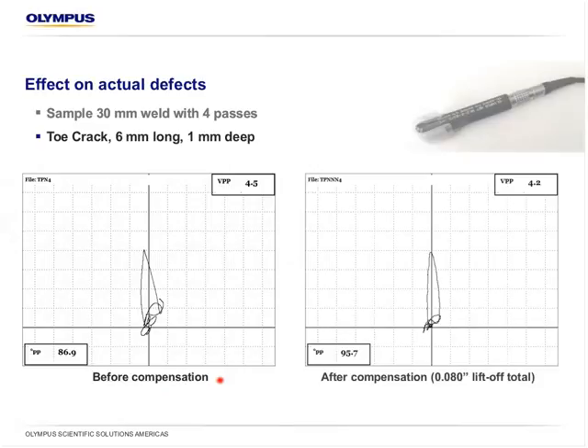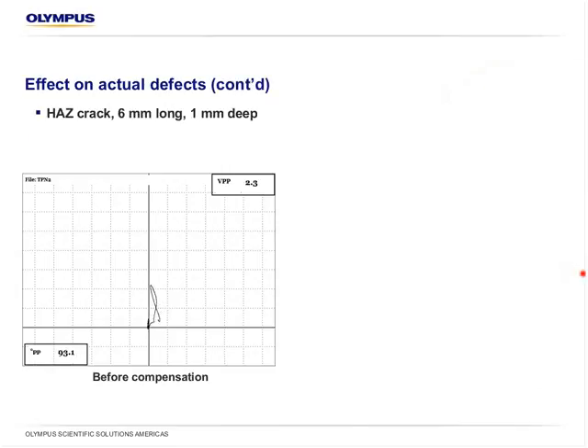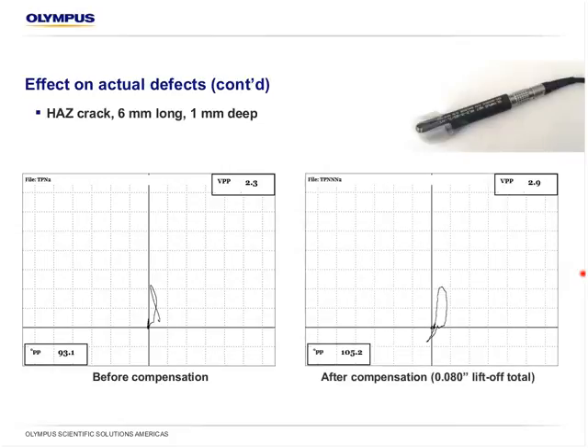And after we scan it with added paint or added liftoff and compensate for this extra paint thickness, basically the idea is that before compensation with very minimum paint thickness and after compensation, if we use the appropriate gain, we can have the same sensitivity. There's no noticeable change in the amplitude of the signal as long as we compensate for the proper paint thickness. Another example, a heat affected zone crack, same dimensions, and again, without and with the paint, the same amplitude is found. So there's no significant change in the signal response.